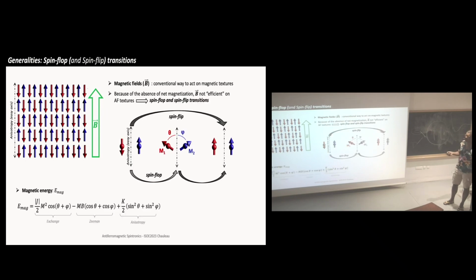Once again, if you're optimistic, you say, well, it's great because they are very robust against magnetic fields. So very silent is cool, but what is difficult is that normally when you want to manipulate magnetic textures, the normal way is to use a magnetic field. But coming to the antiferromagnet, the problem is that the magnetic field is quite inefficient. What happens if you apply a magnetic field on an antiferromagnet? You're going to have 2 kinds of transitions: the first one is the spin flop, and the second one is the spin flip.